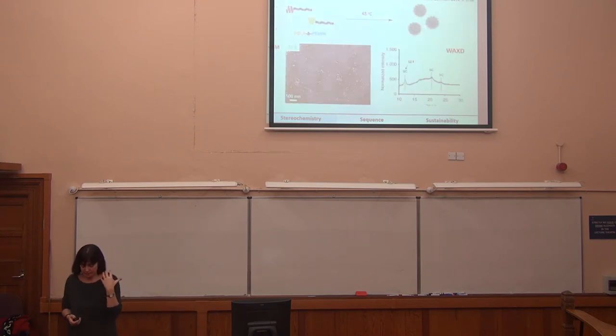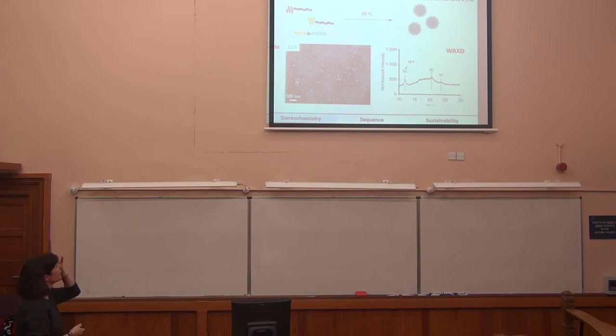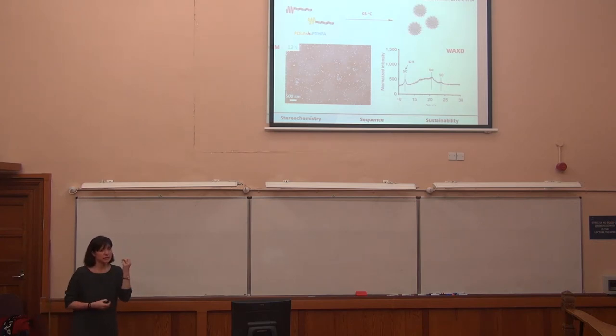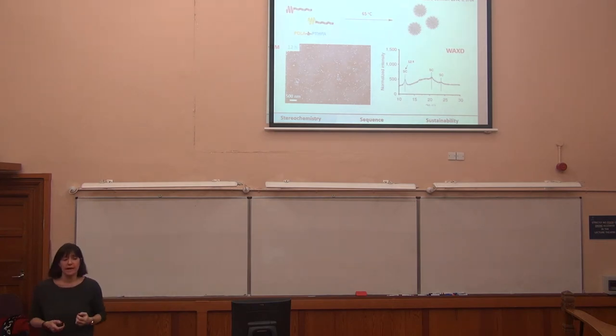And indeed, we actually see some kind of unexpected results in that if we just take the helical L and D polymers and assemble them, we have to use elevated temperature to ensure we get good unimer exchange, and we just form a sort of stereo complex seeds. And these are really, really stable assemblies. They are really robust. We've really challenged them in a number of environments, and that stereocomplexation is a really strong driving force to hold them together, which is really important if you're thinking about them potentially for a delivery application. We can again see very different characteristic signals in WAXS, which show that we have this stereocomplexation occurring.